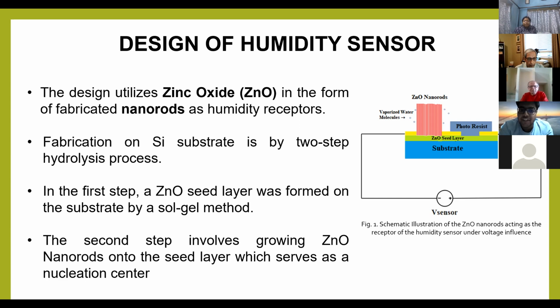Here we prepare zinc oxide nanorods using a two-step hydrolysis process. In the first step, a zinc oxide seed layer was formed on the substrate by a sol-gel method. The second step involves growing zinc oxide nanorods onto the seed layer, which serves as a nucleation center.